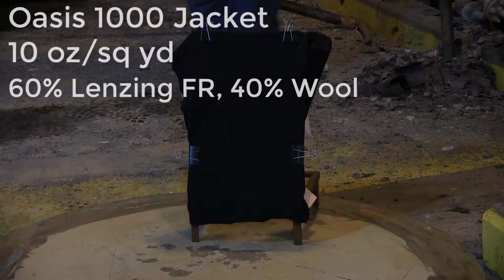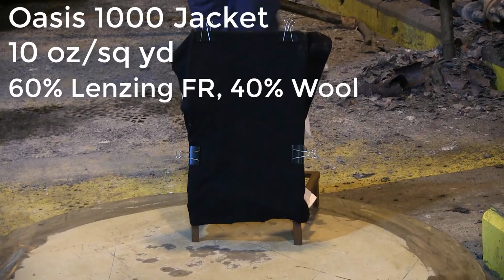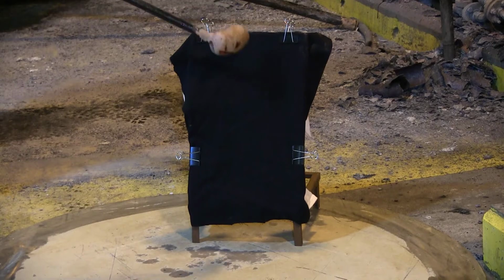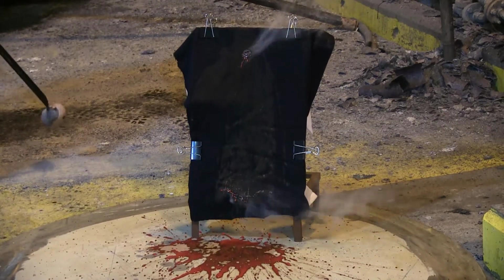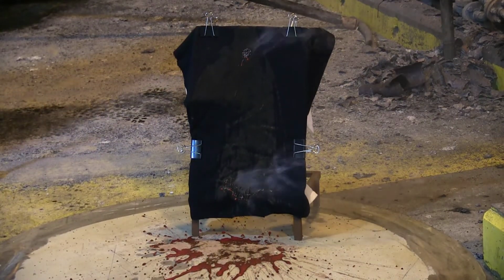Great measures were taken to ensure all materials used were free of moisture. The first material tested was the Oasis 1000 jacket. It is a 60-40 blend of Lenzing FR and wool. Notice how the Oasis does not shrink and the smelt quickly runs off. The collection of smelt at the bottom of the fabric is due to a small lip on the stand.